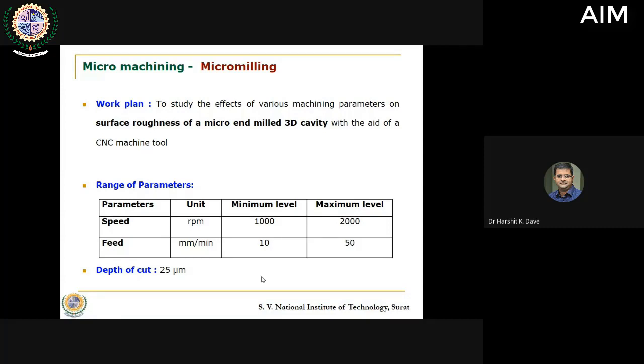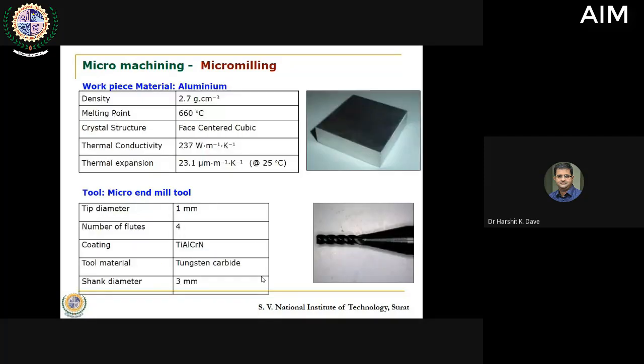We varied the speed between 1000 to 2000 rpm, and we varied the feed from 10 to 50 mm per minute. We maintained uniform depth of cut, that was 25 microns. So in each cut, we tried to maintain 25 microns as our depth of cut. We used aluminum as our workpiece material. We created a specific size of cubic part. We machined it well on all the 6 sides, and then we carried out buffing also so that we could get the best possible dimensional and feature accuracy.